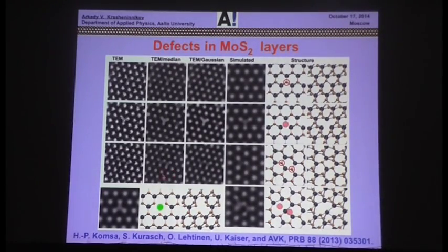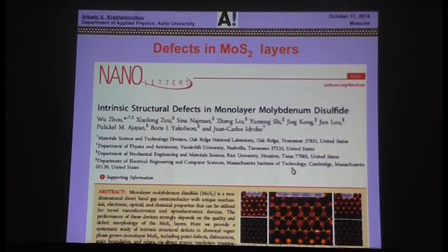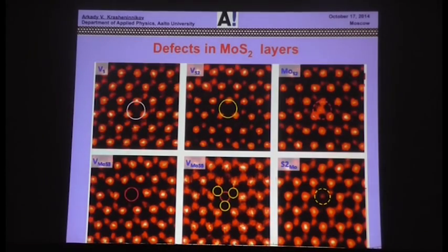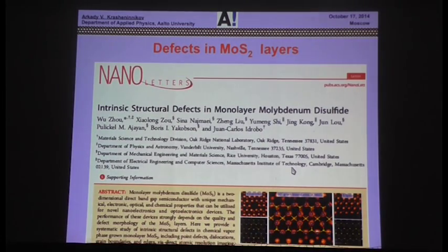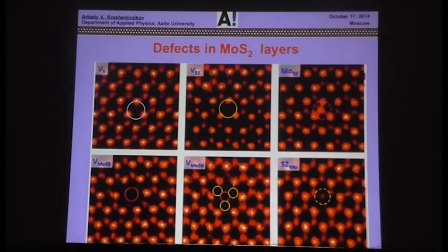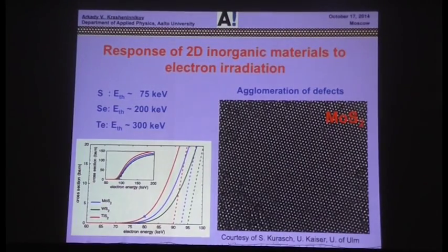Okay, so these are typical defects which appear under the electron beam in the microscope. These are results of our calculations, and based on the calculations we simulated TEM images and compared them to the experiments. And more or less the same results were obtained by a number of other groups. This is an example coming from the US, from Boris Yakobson, and they did calculations here. So nothing really spectacular, point defects, but an interesting thing happens when you keep your sample under the electron beam.